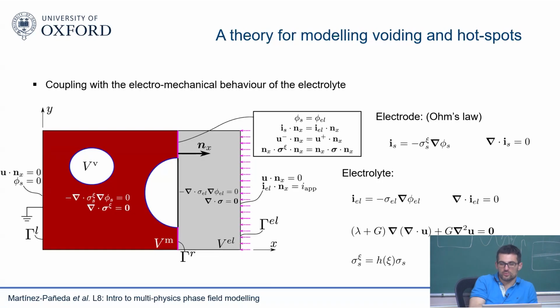So we're going to solve for Ohm's law. We're going to solve here. You see the equations here. So you solve the electrical problem. Careful here, sigma. We use sigma because this is the notation in the community. In both places we solve the electrochemomechanical model. But of course, the one that is stress is the one that has no subscript and that is in bold because it's a tensor, right? So anyway, you solve in the electrolyte. We don't have plasticity in the electrolyte. It's purely elasticity. It's a ceramic.